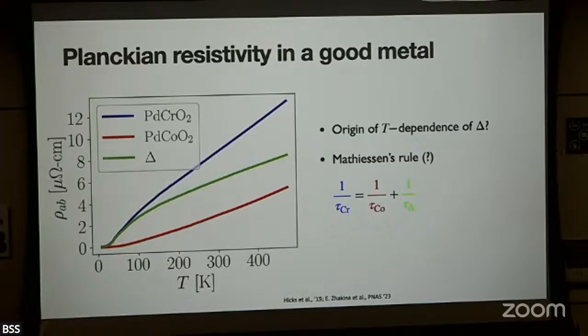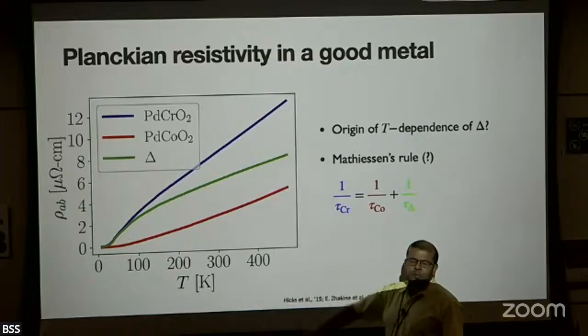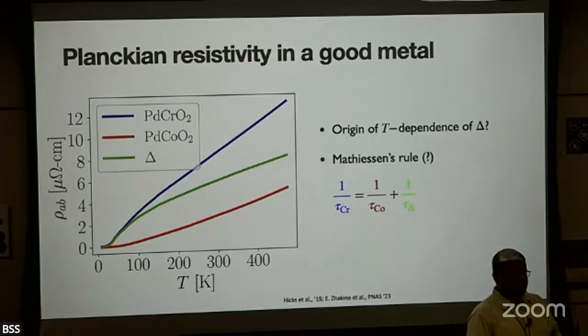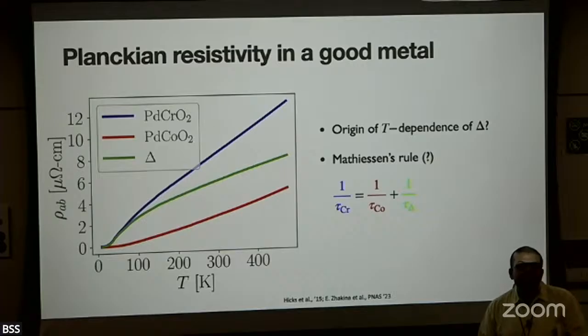I mean, before we talk about nuclear spins, why isn't anyone talking about just the normal local moments? I mean, that's the obvious first step, right? Palladium chromium oxide has these local moments sitting on the chromium sites, which the cobalt does not. These local moments are fluctuating. Surely they're coupled to the electrons in some fashion. You're at temperatures well above the ordering temperature, so it's some thermally fluctuating paramagnet. So could that just be it?